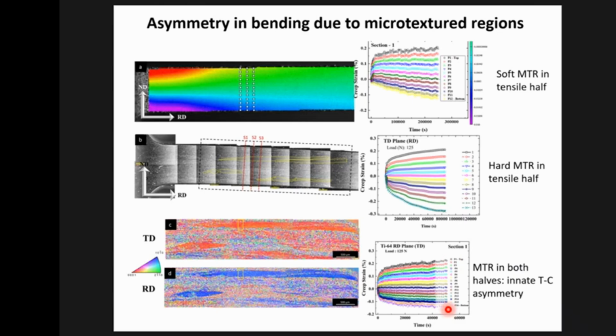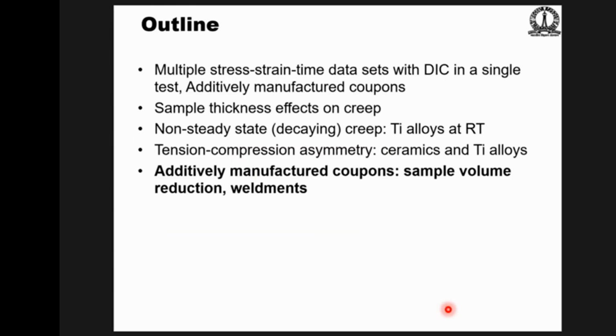By the way, the difference in strains doesn't look very large, but remember that the moment you have asymmetry, the load sheds. So the tensile side actually becomes less loaded, and so the creep rate falls. And the compressive side becomes more loaded, and the creep rate rises. So the strain distribution always remains linear, which means that the tension and compressive strains can't be very different. But the stresses can be dramatically different.